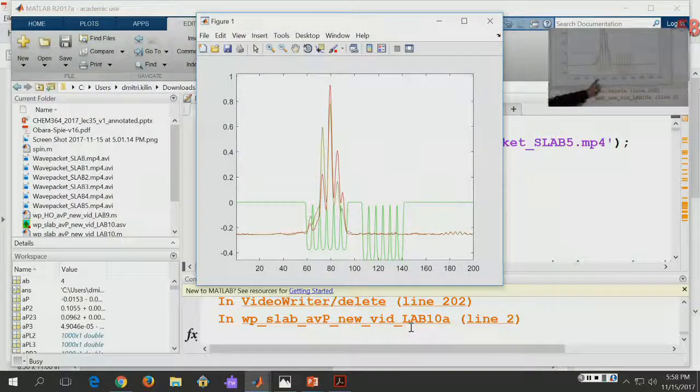So you do see that upon forming of this vacuum or insulating layer, the transfer goes much slower. Although it is energetically favorable to go to another slab, it goes orders of magnitude slower than it was before. So we are like half of the reaction time over, but the electron still stays in the original slab.